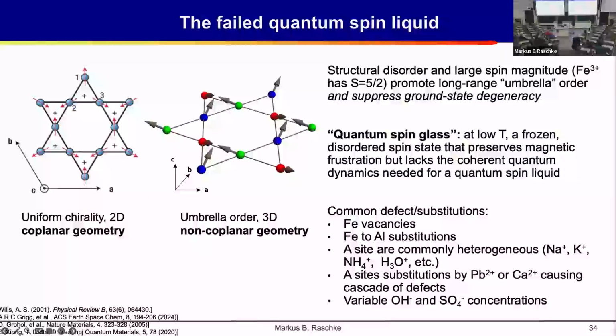Liz is teaching me that there was a problem with this material, though. It forms a Kagome lattice of these iron cations, which sit on these lattice sites. But because of the very strong Fe3+ spin state in these materials, the spins don't stay in this plane. There is a long-range interaction which gives rise to an out-of-plane tilt. And this then freezes the spin, and this is why it turned out to be a spin glass. So this was not quite the solution to the problem. So the search continued.